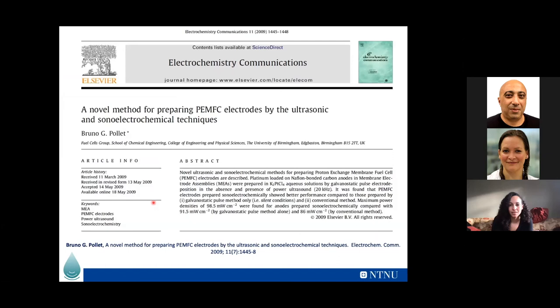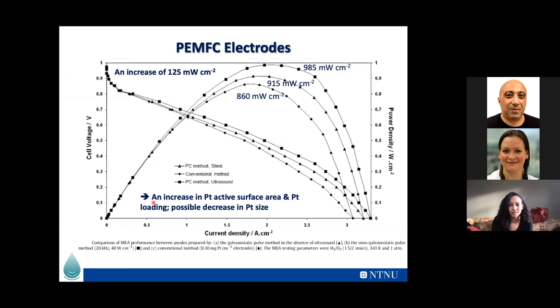So I use, for that instance, a GDE. And I did some IV curve, which is a typical performance curve here, and I looked at it using ultrasound, and it could increase your power to 125 milliwatts per square centimeter.